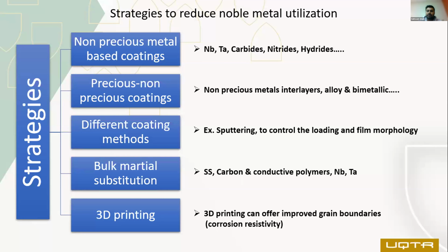Now, how can we further reduce the precious metals utilization? Over time, researchers have explored various methods like non-precious metal coatings, for example, niobium, tantalum, and their carbides, nitrides, and hydrides. These metals have really good potential to replace the precious metal containing coatings, but comprehensive research still remains, because a single cell of an electrolyzer can run up to 80,000 hours.